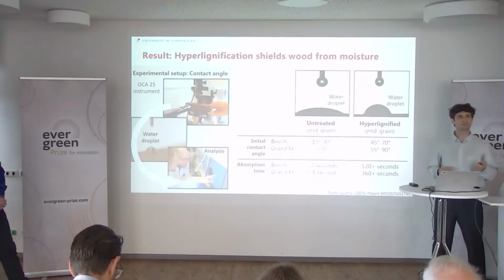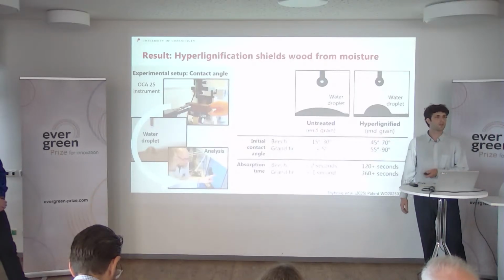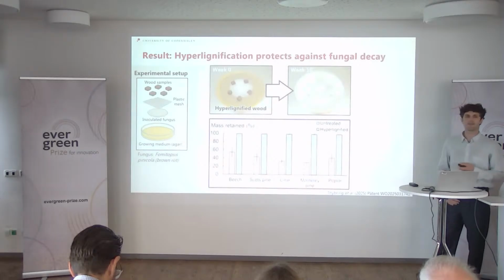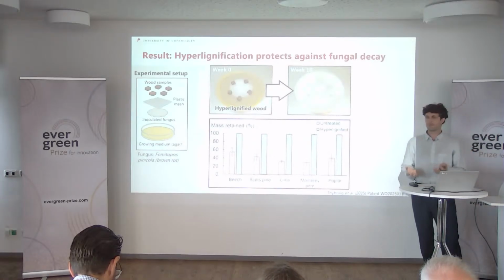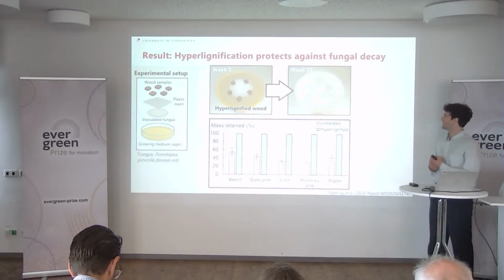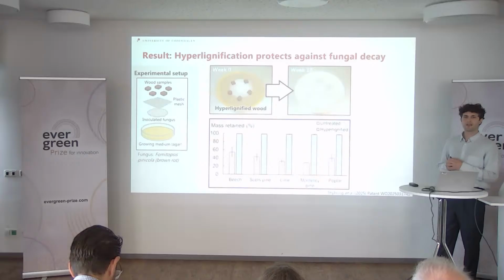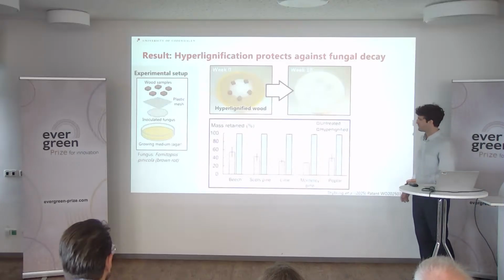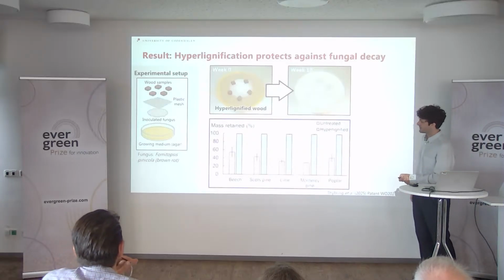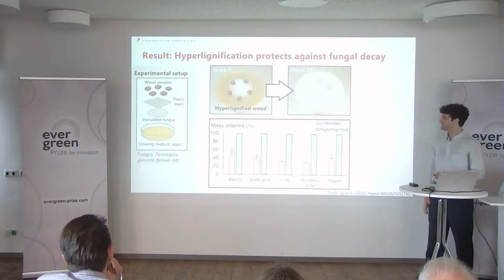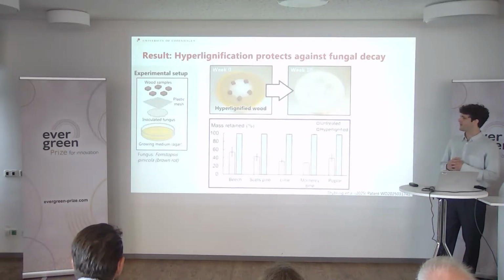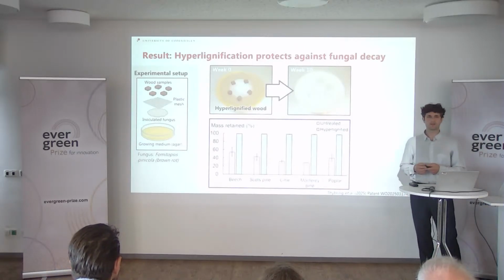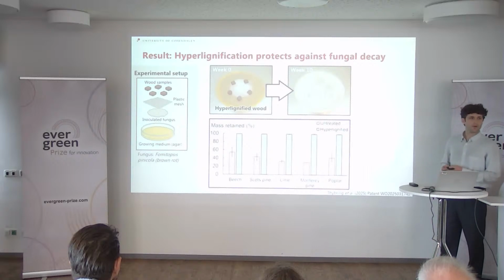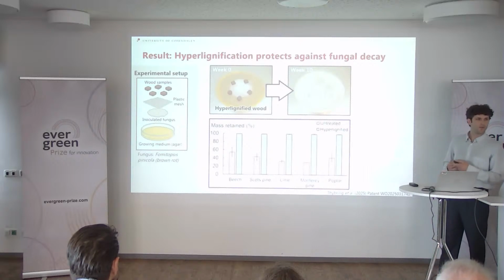Then we took it a step further, and we wanted to address the durability. How does this wood behave against fungal attack? It was our main question to address. So we set up a fungal decay experiment, and we used one very aggressive fungus that we tested in our lab before, which is Fomitopsis pinicola, a brown rot, and we exposed the samples to this brown rot for over 10 weeks.